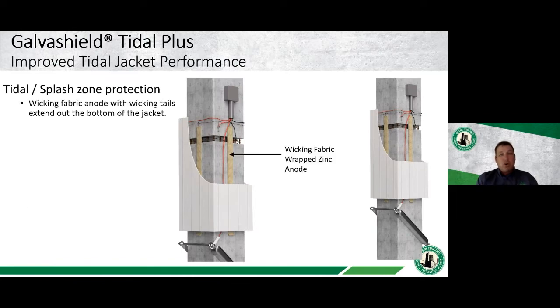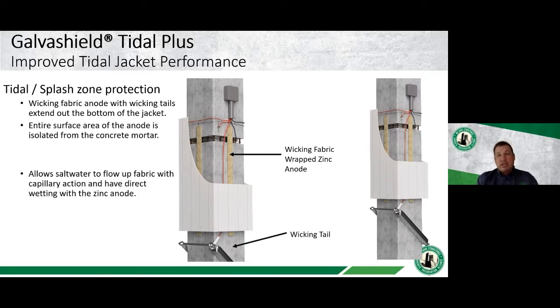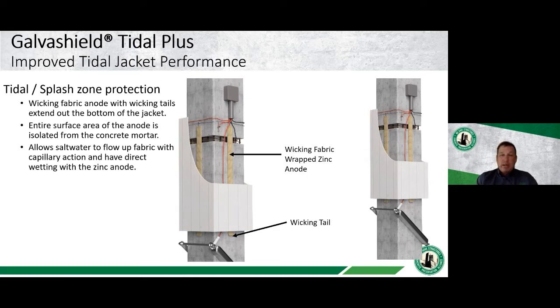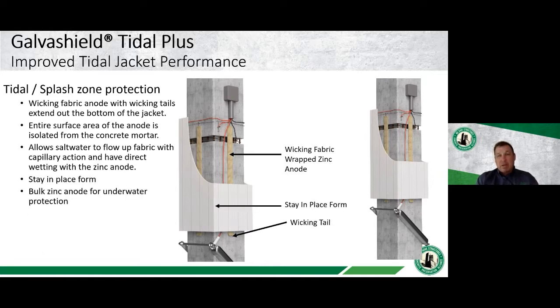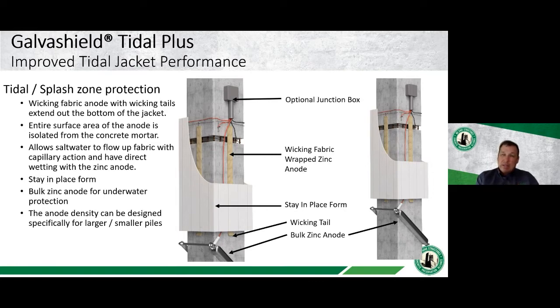So I'm just going to go through some of the components of the jacket system. You have the wicking fabric anodes that are basically hung around the pile, and it can be round piles, square piles, steel piles, H piles, a variety of different types of piles they can be used on. And you have that wicking tail that is extending out of the bottom of the jacket. That wicking tail sticks out, and that allows the salt water to wick up and down that bar anode that's hanging on the pile. So as it flows up and down, it activates the zinc. And all of these anodes are connected at the top to an anode header wire. There's also an optional junction box that can be used at the top, so you can direct connect the system right to the reinforcing steel.